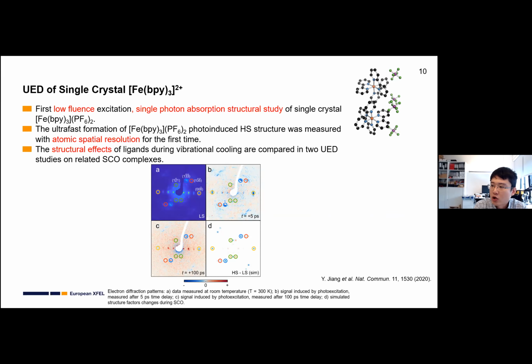And it's also the first time we can really measure the photo-induced high-spin structure with atomic spatial resolution. Because for this iron tris-bipyridine, there's no thermal spin crossover. So people can only do some basic simulation to guess what the high-spin structure is. But by this work, we can actually measure it and tell people what every atom's position is. So later we also discuss the structure effects by comparing two UED results.